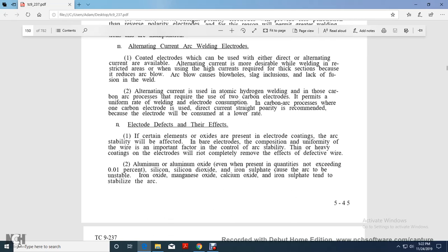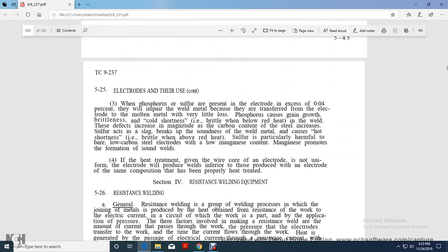Electrode defects and their effects. Certain elements and oxides present in electrode coatings affect arc stability. In bare electrodes, the composition uniformity of the wire is an important factor in control of arc stability, though heavy coatings on the electrode do not completely remove the effect of a defective wire. Aluminum oxide, silicon dioxide, and iron sulfate cause the arc to be unstable. Iron oxide, manganese oxide, calcium oxide, and iron sulfide tend to stabilize it.